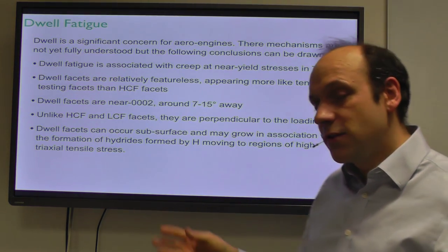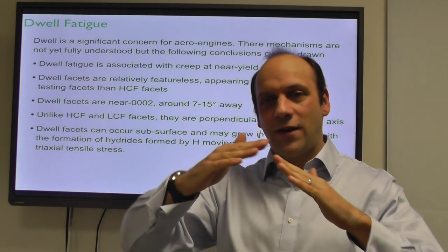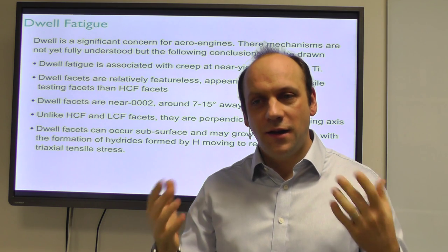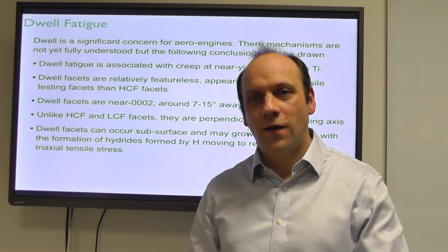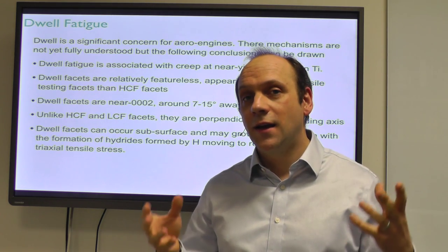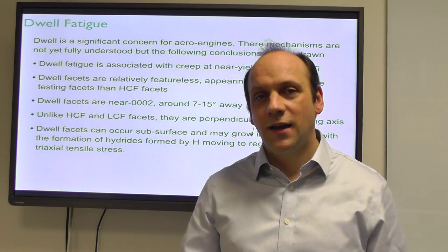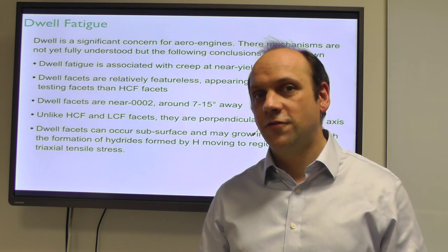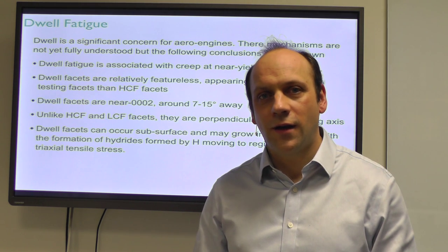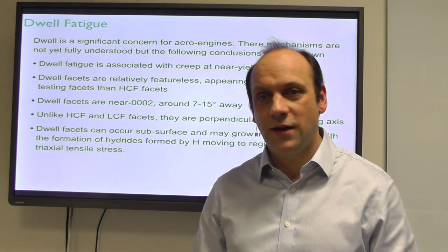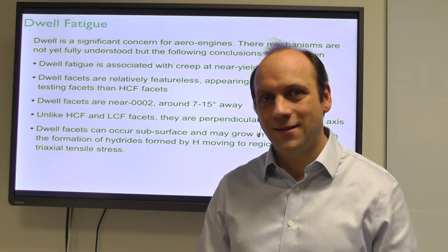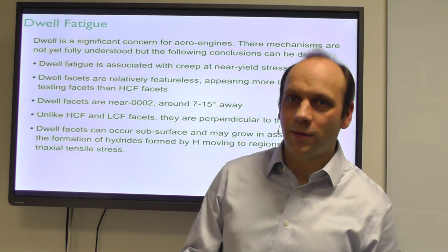And one thing is, dwell fatigue is quite hard to study because you need to have that bad grain pair, or at least so the hypothesis goes at the moment. And so you need to test quite a large volume of material to find the worst pair in a large volume of material. So what you see is that discs in spinning rig tests tend to fail at lower stresses when they're dwell fatigued than you find for test pieces. And test piece specimens may not be, therefore, representative of what's going on in discs. And that makes it a very complex and difficult problem to study.